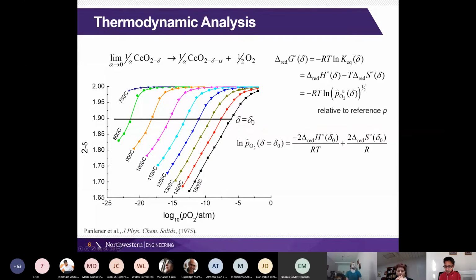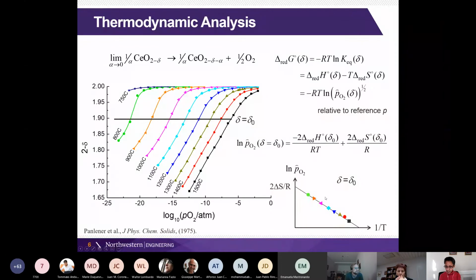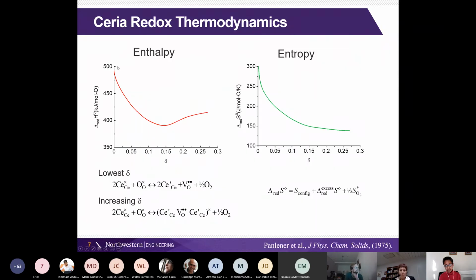All we're doing is saying, okay, let's rewrite this expression here, putting these two together, evaluate it at this given value of non-stoichiometry. We're going to put this together on an Arrhenius plot. So we're looking at all the pairs here of data points. We plot a line from that, and then from the intercept, we're going to get the entropy, and from the slope, we're going to get the enthalpy of this reaction. So we're going to do this now at all sorts of different values of non-stoichiometry, and out of that, we extract the enthalpy of reduction and the entropy of reduction as functions of oxygen non-stoichiometry.